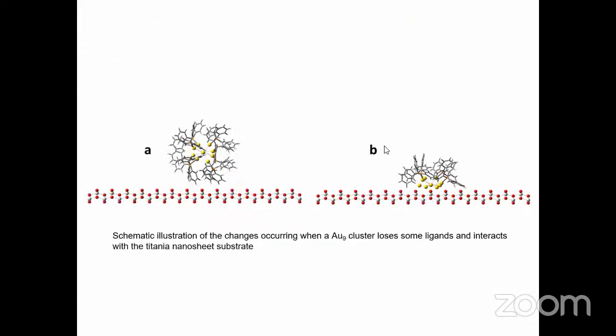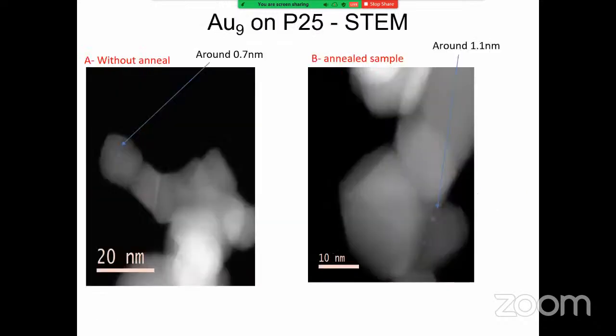Which means that at the beginning, we have a 3D structure with the ligands. When it interacts with the surface, or any of the ligands are removed, it changes the structure of this nanocluster. We also deposit them on the P25, which is the titanium nanoparticles. And we can show a difference before removing the ligands and after removing the ligands. And we saw some aggregation. And this is also the STEM image: the large one is the P25, and this one is the gold nine deposited on top of the P25, which is the titanium nanoparticles.